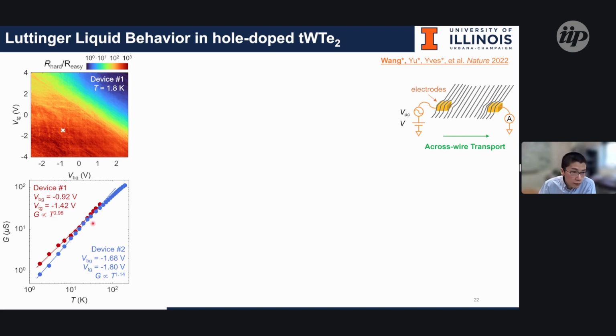What we observe is that with the temperature dependence, we observe power law behavior, which is very rare in a two-dimensional system. You can see that the resistivity, or conductivity, or conductance follows a power law of one, and this power law can be extended over 1 decade of the temperature range.